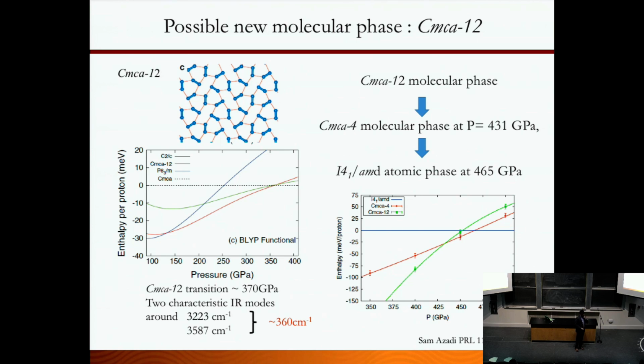On the other hand, let's assume these critics are correct, even if it becomes a metal, the layer is going to be really small. We're talking about 50 nanometers, but at 500 GPa it's going to be much smaller than that. Even hydrogen, we start at 10 micron size, but by the time you get to 500 GPa, it's like 1 micron. So even if you make hydrogen a metal, it's going to be thin enough to be transparent. The skin depth is so high, you will see through it.